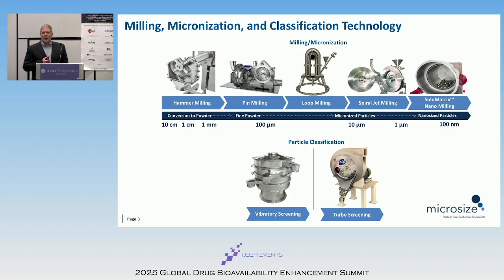And then we've onboarded the Solumatrix platform, where they can make nanoparticles. And this is just pure powder on powder. There's no liquid involved to serve as a media. So it's basically your API, your excipients, and then stainless steel balls to grind the material into a powder. And this powder is directly compressible into a tablet, so there's not a drying step needed.